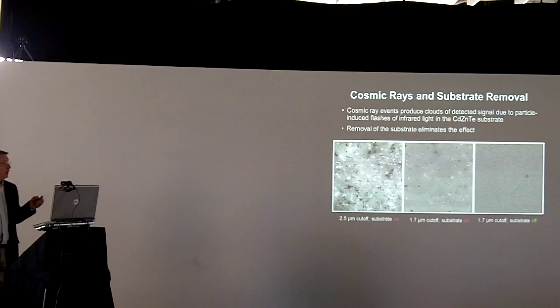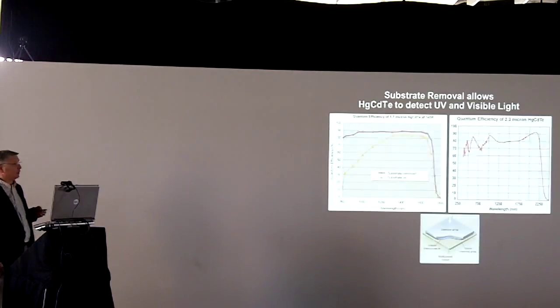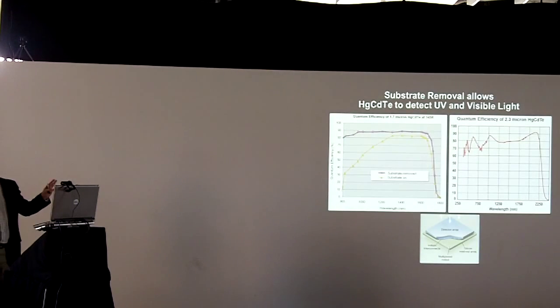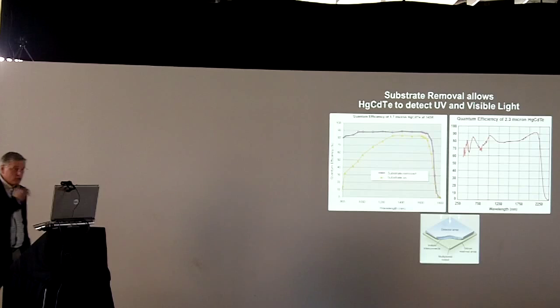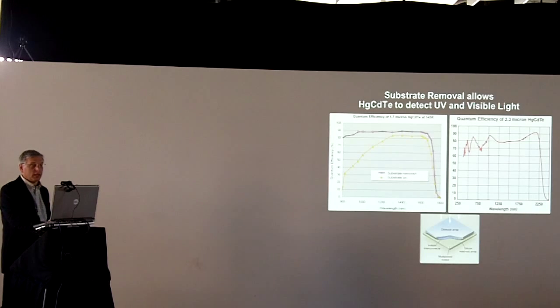of your infrared detector. There's another benefit for doing this, and that is that the CdZnTe absorbs visible light. So if you look over here, visible light's 400 to 700 nanometers, and CdZnTe absorbs shortward of 800 nanometers. And this has the substrate on, where the quantum efficiency here, the amount of light you're detecting, as a function of wavelength. You can bring the quantum efficiency up to 80 to 90%. You can put on a better anti-reflection coating. You can remove defects at the surface.